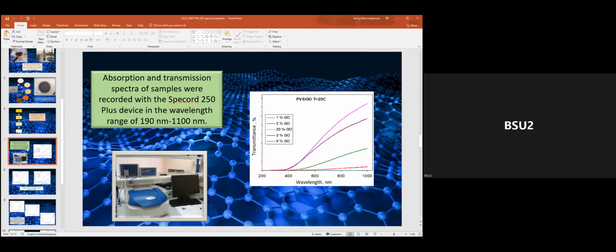Absorption and transmission spectra of samples were recorded with the Specord 250 plus device in the wavelength range of 190 nanometer to 1100 nanometer. Here, transmittance spectrums for polyvinyl alcohol films with different concentration of graphene oxide are shown. The maximum transmittance was observed for graphene oxide polyvinyl alcohol with 1% concentration. It is 14.78%.